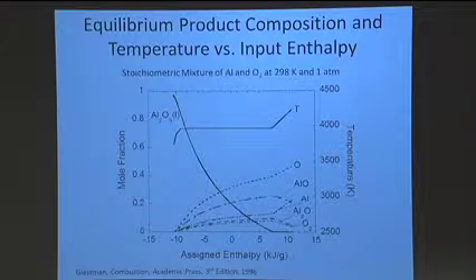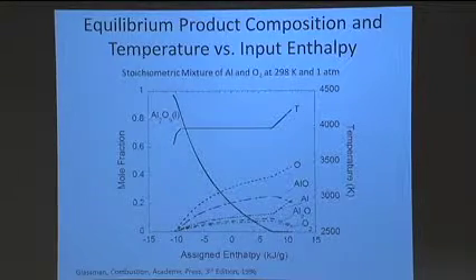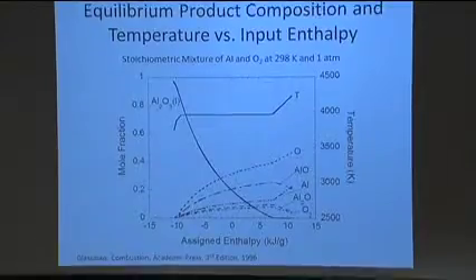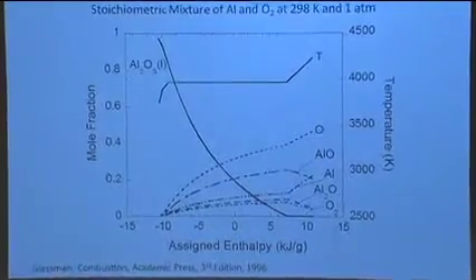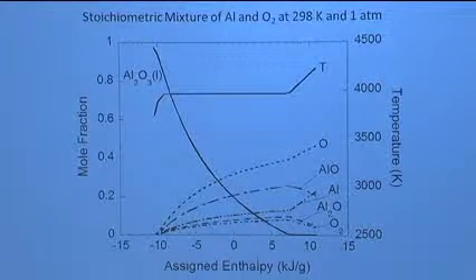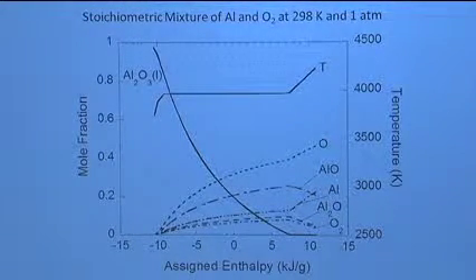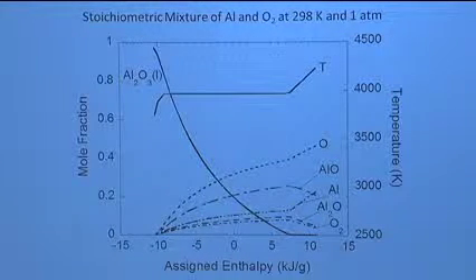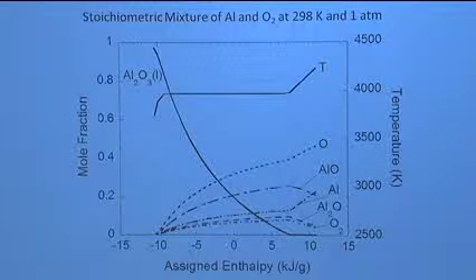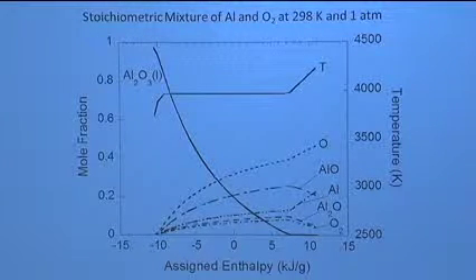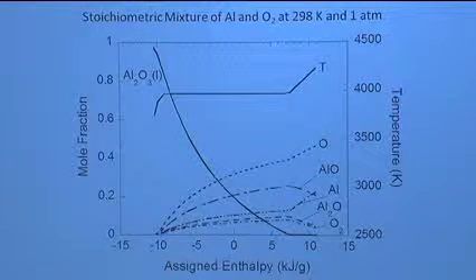Okay, this is another interesting plot that Professor Glassman and Paul Pappas actually looked at early on. And this is the idea of looking at this limiting flame temperature concept in these metal reactions. And what I've done here again is I'm looking at essentially an equilibrium analysis where I'm changing the amount of energy that I'm adding to the initial reactants, either by adding energy to the reactants or removing energy. And so if I look at the case of 0 here, this is when the reactants are, say, at 298 Kelvin, and these calculations are at 1 atmosphere. So this would give you basically the flame temperature that I showed you previously, and this would be the composition. And what you can see here, under these conditions, some of the condensed phase alumina has been dissociated, and I'm forming species in the gas phase as I dissociate.